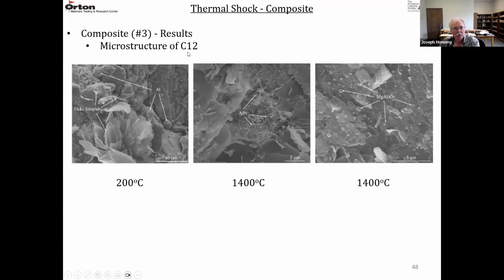So they looked at the microstructures, and this is C12 at 200 and at 1400 degrees C. You can see these spherical particles. Oh, that's the aluminum metal. And these plate-like structures are the flake graphite. There's some aluminum nitride whiskers that are starting to form here. This is 40 microns. This is higher magnification, 5. And then this bar is 5. And then they're showing these little particles, spinel forming on top of the MgO particles.